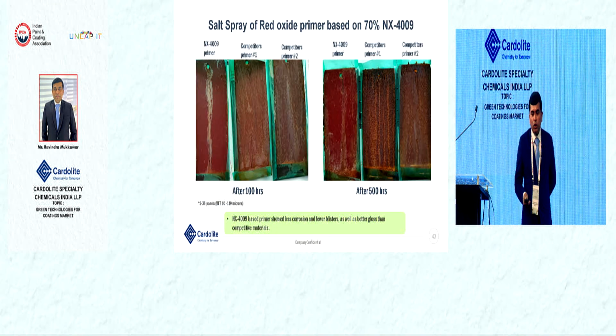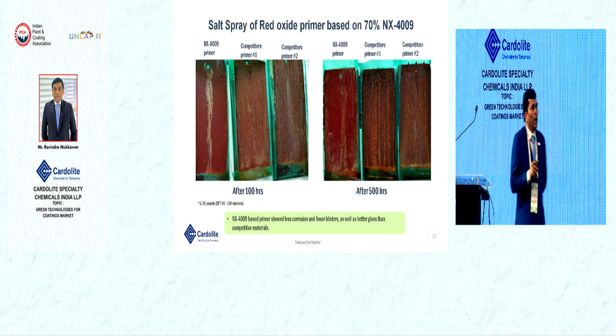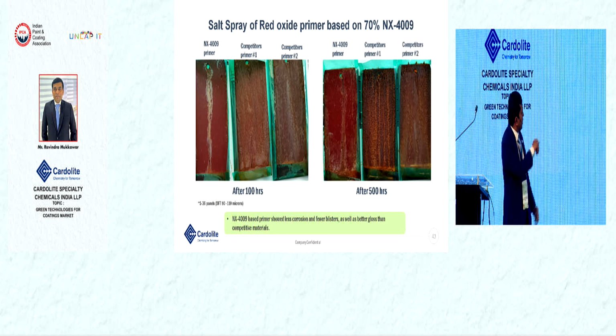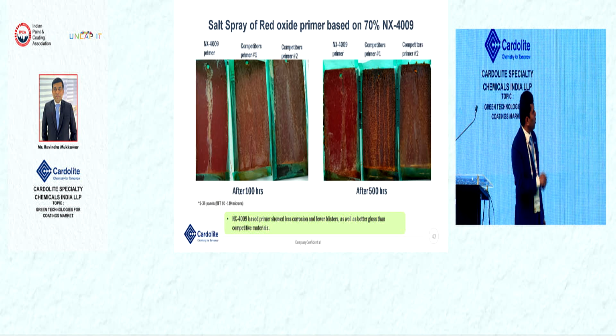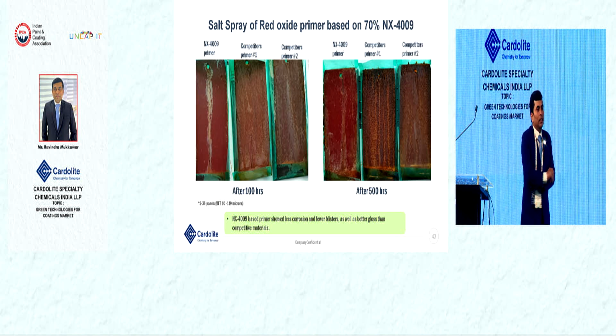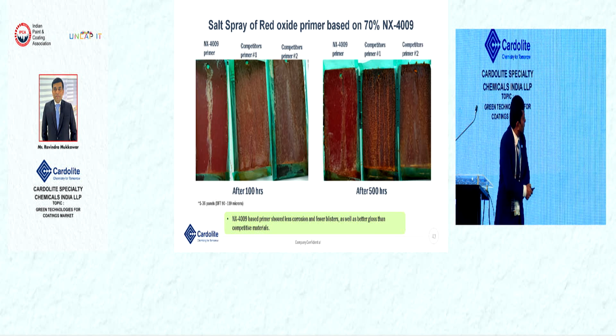So we check the salt spray as I mentioned. We check the 100 hours test and then we extend the accelerated test up to 500 hours. There is no corrosion using our NX 4009 because of the cardanol-based resin in this product.